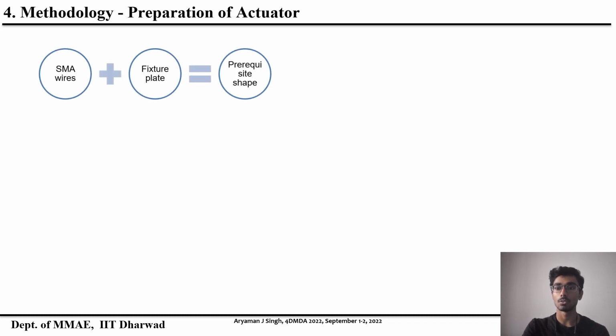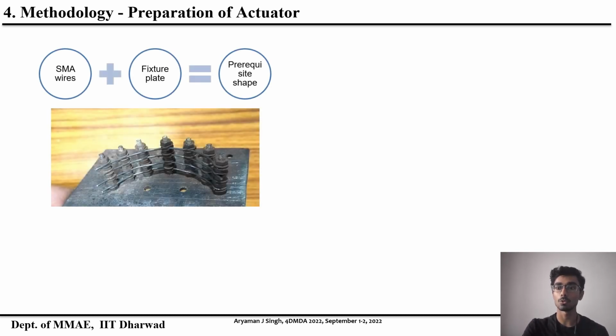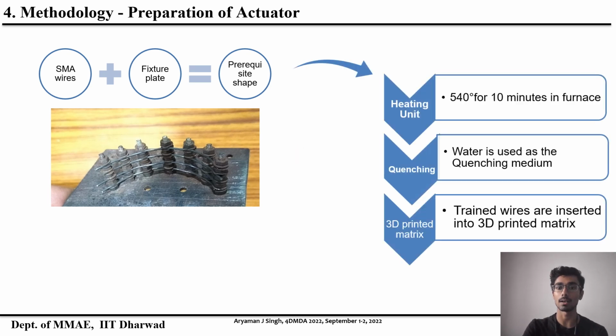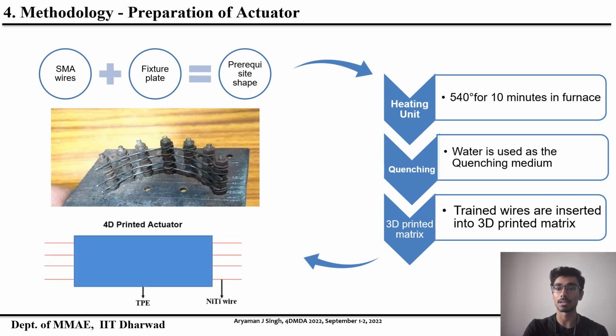To prepare the actuator, we first created the fixture to train the SMA wires. Four such wires of 75 mm length were placed in the fixture as shown, with a bending angle of 70 degrees. Then the fixture was heated up to 540 degrees Celsius in a furnace and immediately quenched afterwards. As the wires were trained, they were finally inserted into the TPE matrix.